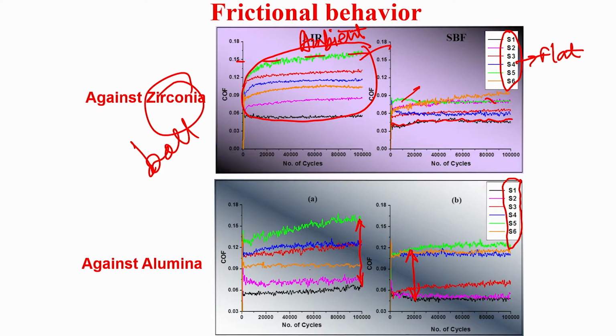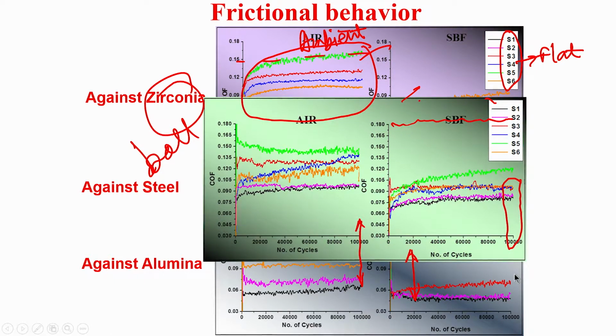So this 0.9 window, the difference in the coefficient of friction, steady state coefficient of friction, is reduced to 0.04. In case of steel against steel counterbody, some of the high coefficient of friction is like 0.15, but even the green one, S5, goes to 0.11. This reduction may be little lower in case of the steel counterbody, but certainly if you compare ambient versus simulated body fluid, there is a push towards a lower coefficient of friction in SBF.